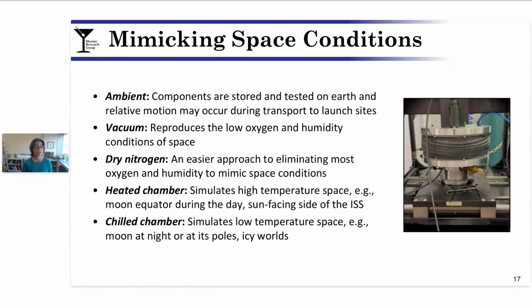We'd like to perform testing here on Earth in a vacuum-controlled environment to mimic the low oxygen and low humidity conditions of space, as well as the low pressure directly. Or an alternative, easier approach is to test in dry nitrogen, where test chambers are flooded with nitrogen. Again, the goal is to remove the oxygen and humidity to mimic the space condition in a little bit easier to access approach. We've already talked about temperature. It can be very hot, it can be very cold, and these types of conditions can be mimicked in specialized chambers here in a terrestrial environment.